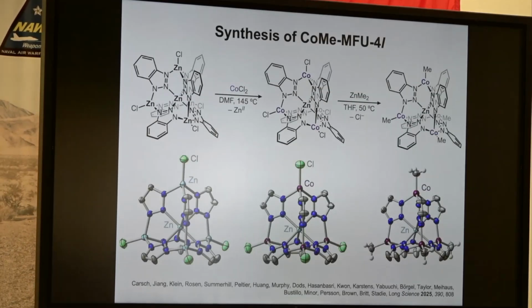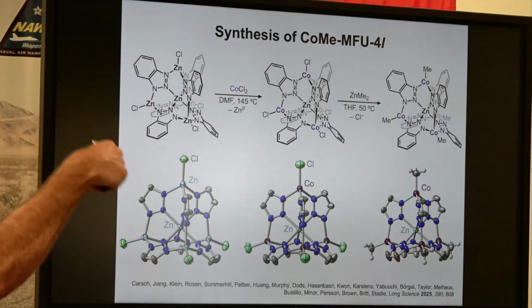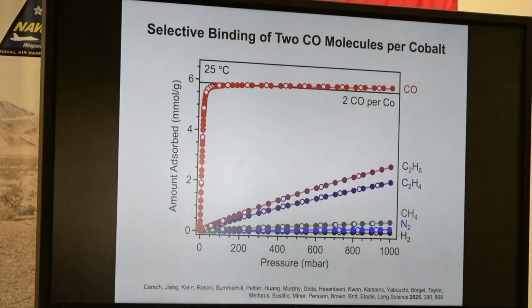Last thing on these MOFs for gas separations. Can we make MFU4L behave in a cooperative way? Can we create a step in these materials? We don't have chains of metals. We have 4 per tetrahedral cluster. There is one way we can do that to start, and it happens if we make the methyl, first we replace zinc with cobalt, then we replace chloride with a methyl group, and that cobalt methyl group for tris-pyrazolyl borate complexes was known to react with two CO molecules reversibly. We can do the same thing in the MOF and create a very high capacity where every cobalt with a methyl grabs not one but two CO molecules. You double your capacity per metal.